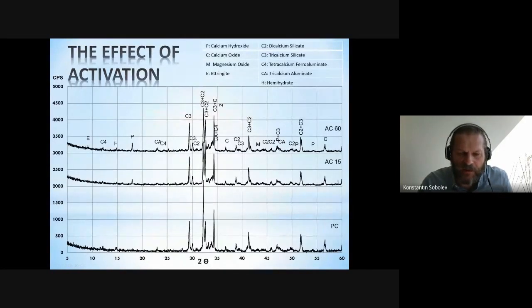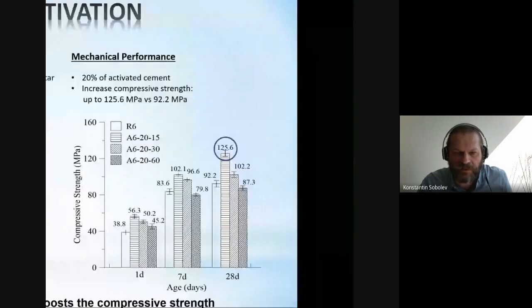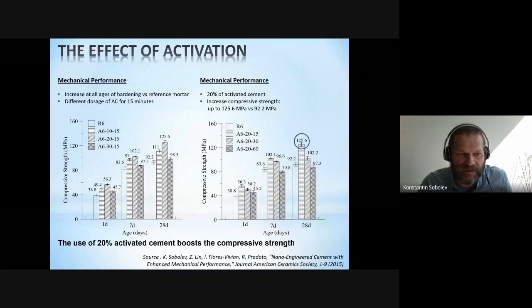Due to mechano-chemical activation, you can see that the degree of hydration is considerably increasing, and after 60 minutes you can have considerable volumes of products of hydration. You can see Portlandite, you can see ettringite appearing, and the main peaks of C3S and C2S are really reduced after 60 minutes. So obviously Portland cement can be used as a precursor for nanoseed production.